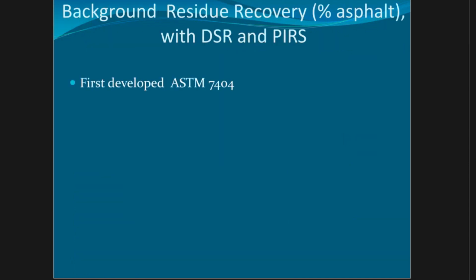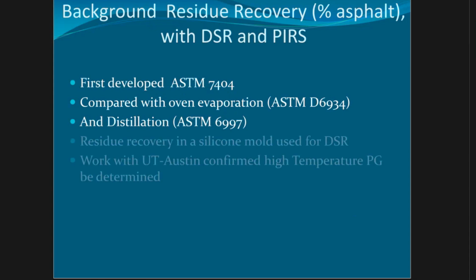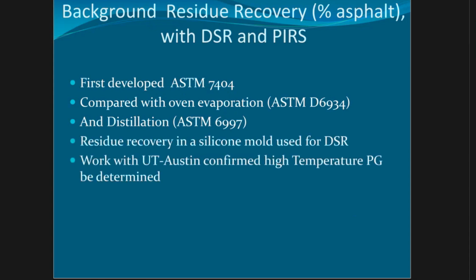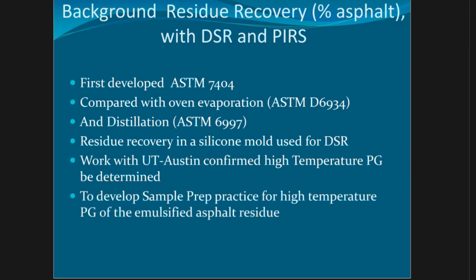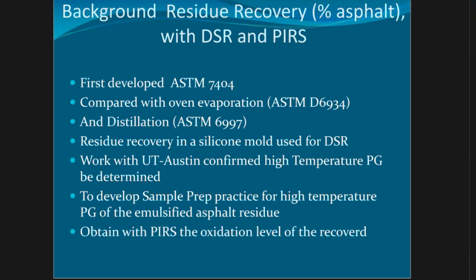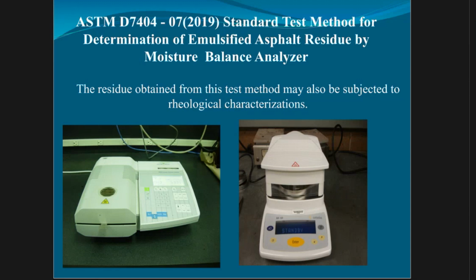The background to this is that there's a standard at ASTM for the moisture balance analyzer. We did a comparison of that. In standard 7404, embedded at the bottom, there's a diagram which I'll show shortly, comparing one of the methods used right now. What we have butted onto this is the PIRS as a conceptual thing, with the moisture analyzer.